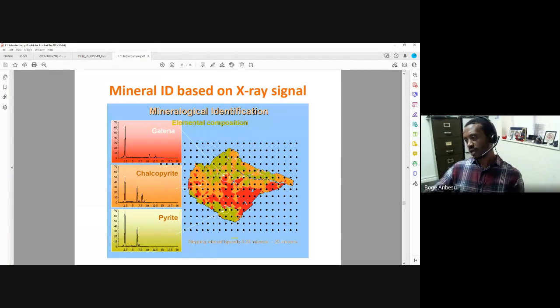For example, when you look at this, you can see the orange, the red, and the green are very intimately intertwined with one another. It's a complex association. And that's one of the pieces of information we get from mineralogical work. So before I decide on my grinding mill, I already know that grinding is going to be a lot more complex, because the particles I'm looking at tell me the grains of chalcopyrite, pyrite, and galena are very fine. If I did grinding to 500 micron, it's not going to help, because all these minerals will still be together at 500 micron.